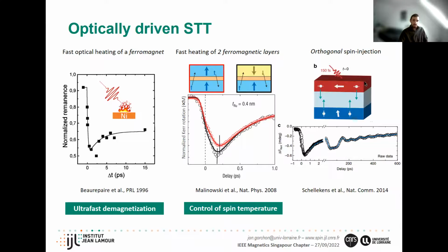So in a way, by just exploiting the spin currents, you can control the spin temperature. And a few years later, again, the same group, this is the group of Bert Koopmans, tried this orthogonal configuration and demonstrated that you can initiate some dynamics due to spin transfer torque. So basically you get some spins that are pointing up that go here and torque this layer and vice versa. And so you get this complicated dynamics, because here you're probing the 2 layers. So you have to deconvolute the dynamics of the bottom layer and the top layer. But they did this very nicely, and basically they demonstrated that they were having ultra-fast spin transfer torques.